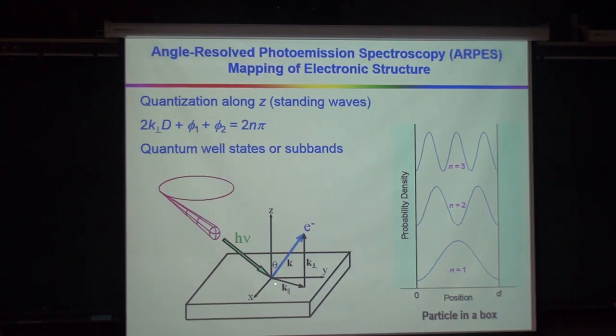Now we are dealing with thin films, so the case is very simple. Let's assume that we look at the normal emission, that is, the electrons come out perpendicular to the film. You can imagine that along the perpendicular direction, with the top surface and bottom surface, the electrons are confined as if they go back and forth, forming a standing wave. So we see these standing wave patterns, from state 1, state 2, state 3, so you can actually see these in the film. You just measure the photoemission, you can see these discrete states come out, and you subtract the energy of the photon, you back it out, and you get the original energy states in the ground state. That's how we do it.